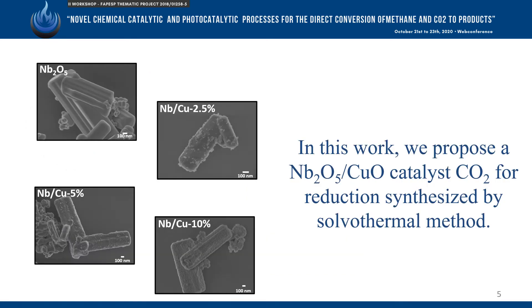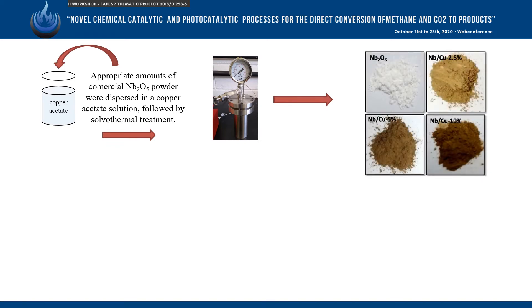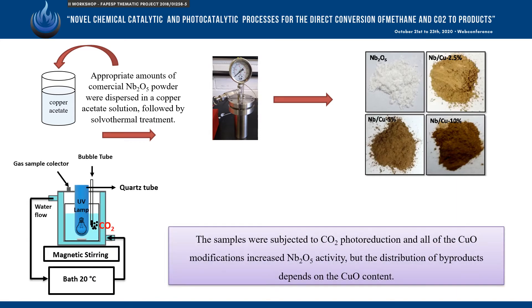In this work, we propose a niobium pentoxide/copper oxide catalyst for CO2 reduction, synthesized by a solvothermal method. Appropriate amounts of commercial niobium pentoxide powder were dispersed in a copper acetate solution, followed by solvothermal treatment.